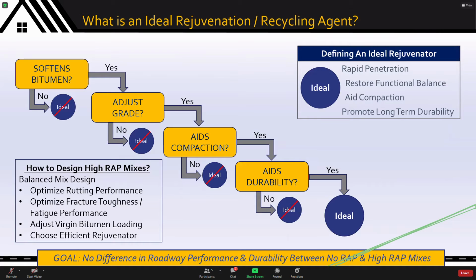A couple of key points to remember while you're designing high RAP mixes: you need to adjust your virgin bitumen loading. This is because you are now asking your rejuvenator or recycling agent to make more and more of the RAP bitumen, the hard, stiff RAP bitumen, contribute to meaningful, effective properties. So you should adjust your virgin bitumen loading. And finally, you need to choose an effective rejuvenator that helps to achieve all these balance of properties.